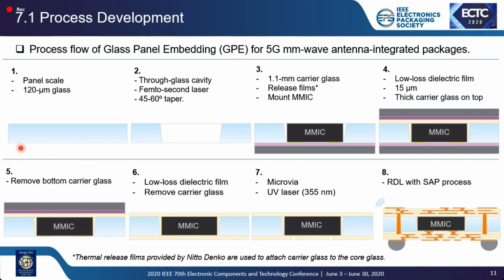So we have a panel glass, which is 120 micron thick, and we drilled a glass cavity using a femtosecond laser, and we attached the thick 1.1 millimeter carrier glass from the bottom side using a thermal release film provided by Nitto Denko. And we mounted an MMIC, in this case an LNA, face down. And we laminated a low-loss polymer, which is Taiyo Zeristo, from the top side.